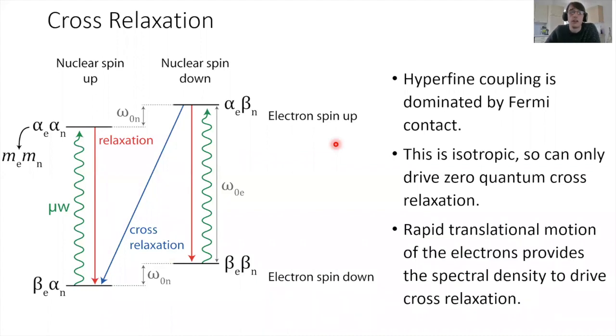The other thing we need in order to get this cross relaxation is spectral density at this transition frequency. In metals, that comes from rapidly moving electrons at high kinetic energy, and so that's where that spectral density comes from. This is in contrast to the Overhauser effect in insulating solids, where I believe it's still an open question where that spectral density comes from. But in metals, it's very well understood that it comes from rapid motion of the electrons.